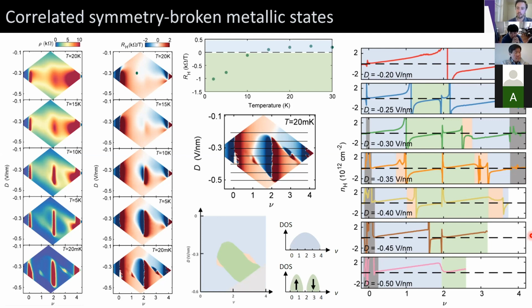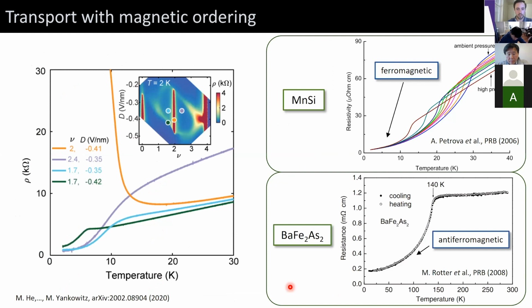All right, and so I want to return now to the question of why we have these abrupt drops in resistivity. And one important feature of this system is that from in-plane magnetic field measurements of the energy gap at half filling, we think that these bands are spin-polarized. So this energy gap represents a spin-polarized excitation. And so if we're probing just a single one of these bands, it's valley unpolarized, but it should be spin-polarized. And so there's some sort of magnetic ordering that we anticipate in these metallic regions within this halo that are neighboring this correlated insulating state at half filling.